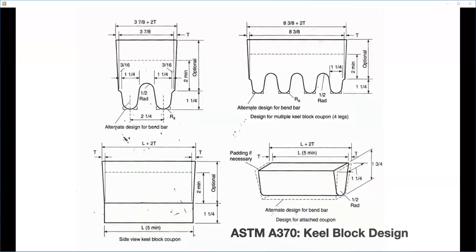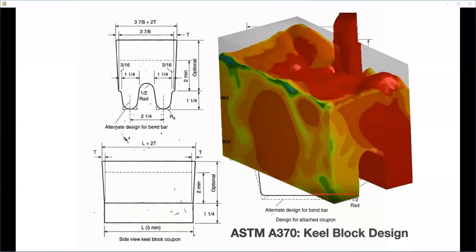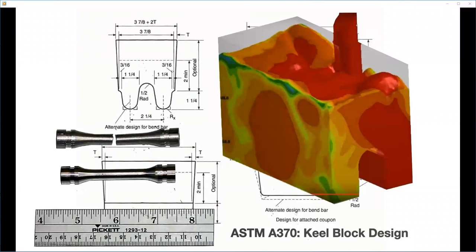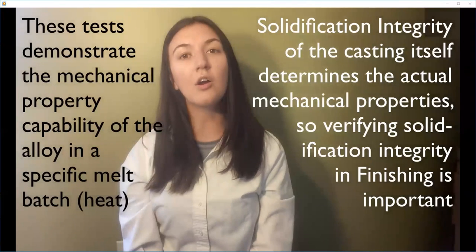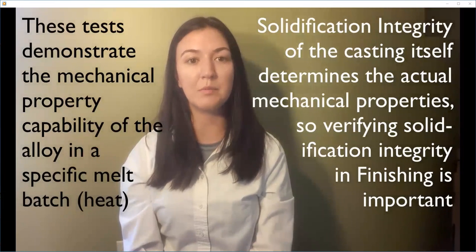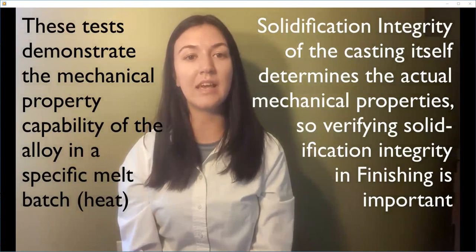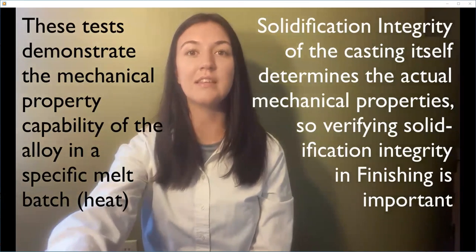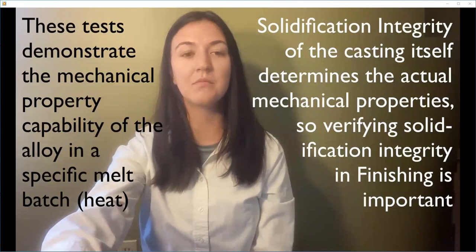Since verification of heat-treated properties is usually accomplished with test coupons that are cast separately by one method or another, the properties from tensile tests, impact tests, and bend tests, for example, are representative of the alloy's capability, not necessarily a local high-stress region in the actual castings.